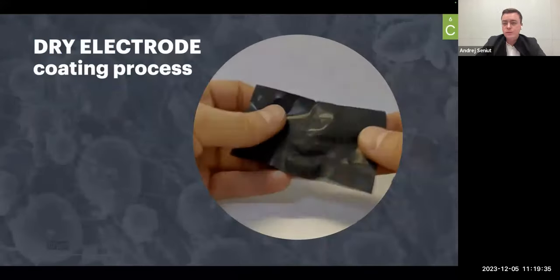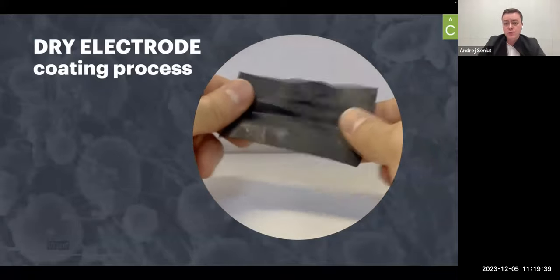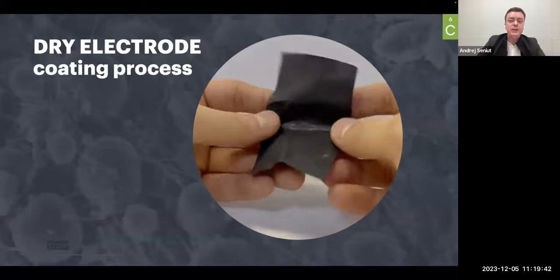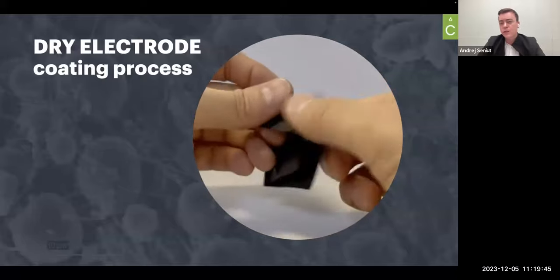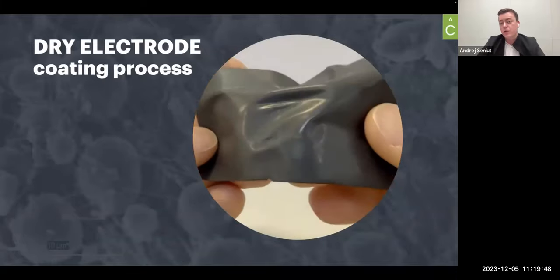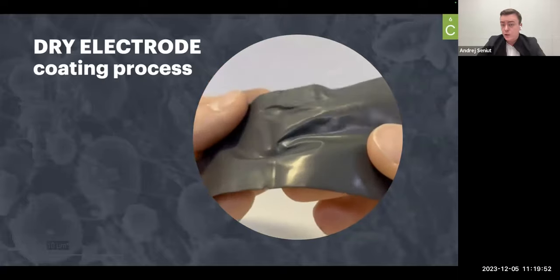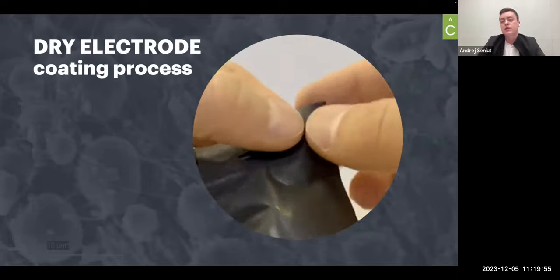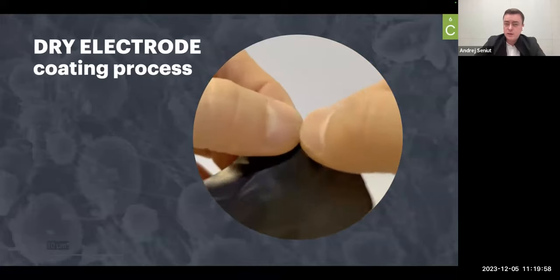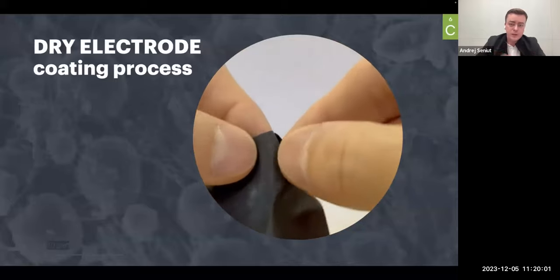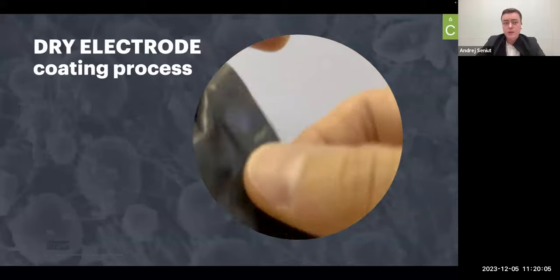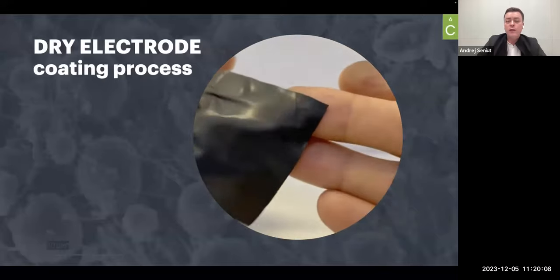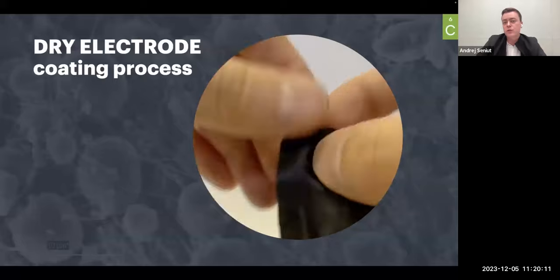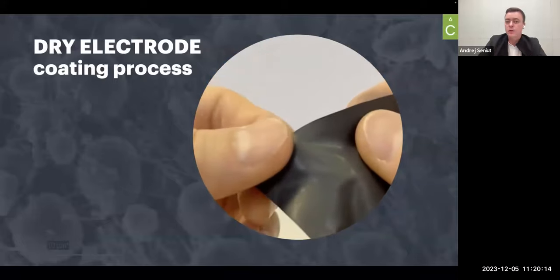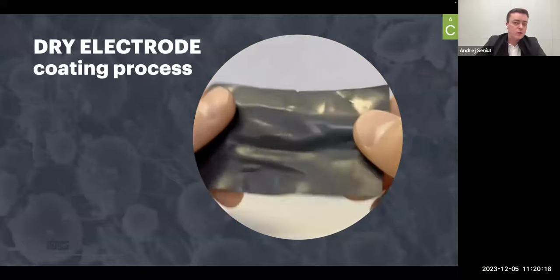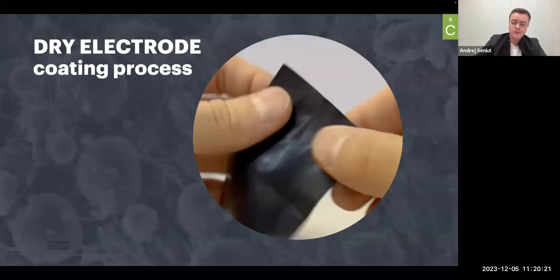Just to show you the proof of concept result which we have achieved in our laboratory. So this is a freestanding dry cathode, NCM811, with about 1% of PTFE and with single carbon nanotubes inside, with a very high thickness. As you can see, this electrode is quite flexible and quite durable, and we tested its basic electrochemical performance, and the cathodes work pretty well. And now we are developing solutions for anodes, where we're trying different approaches, for example, coating the active material surface with TUBALL, or creating concentrates for anode applications as well.